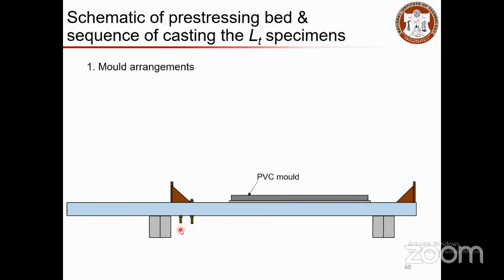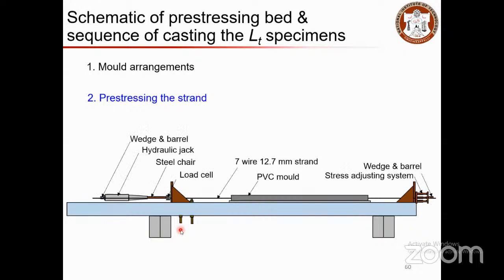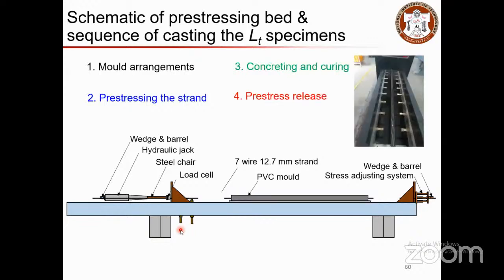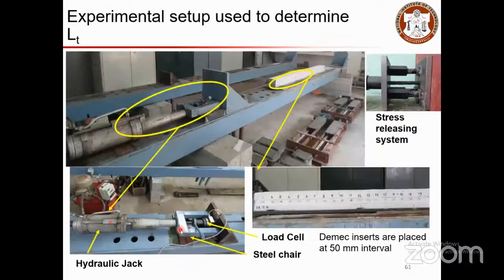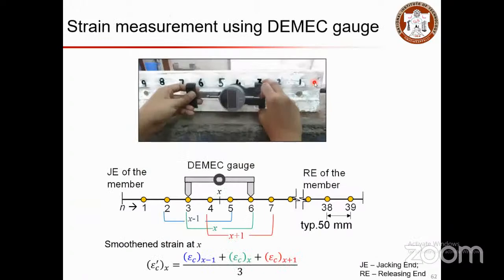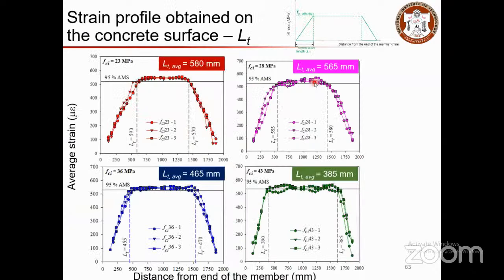You have a pre-stressing bed and you have a mold placed. Then you pre-stress the strands using the hydraulic jack and other accessories required to activate the stresses, and you concrete it and cure it. Then you cut the sample. And in this method, I placed inbuilt Demec pins, which are required to measure the strain on the concrete surface. You will not be measuring the strain directly; you measure the change in distance and then you calculate the strain. So these are the ways in which strains are obtained.